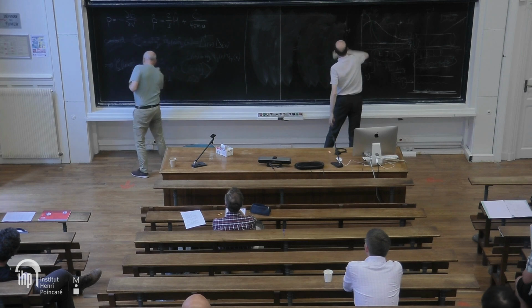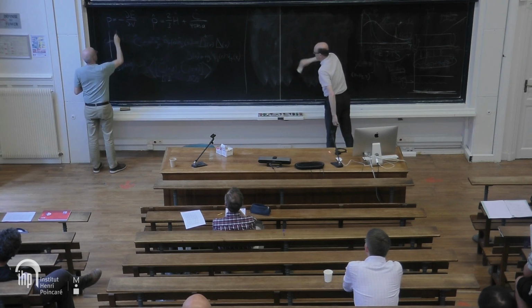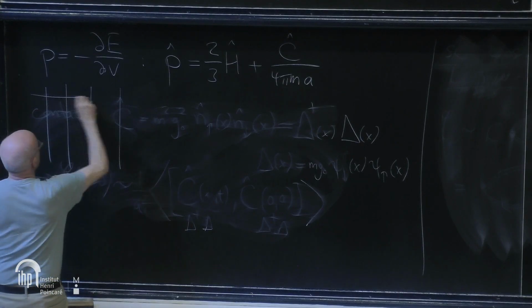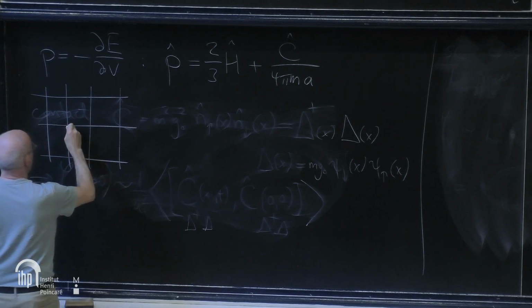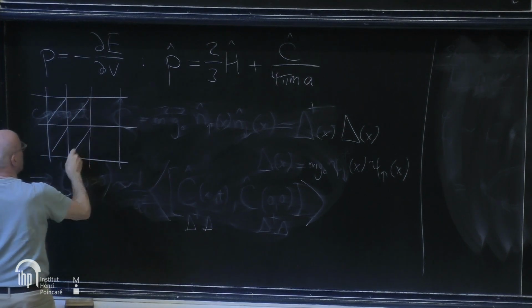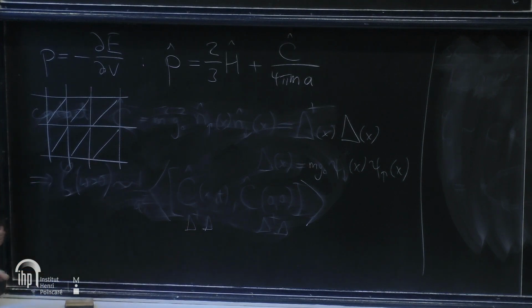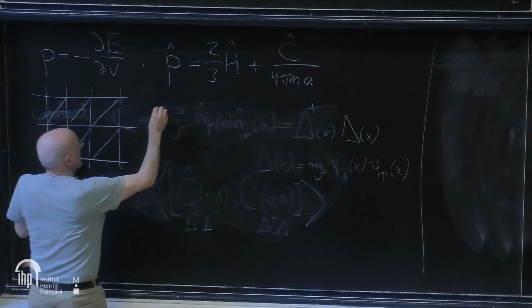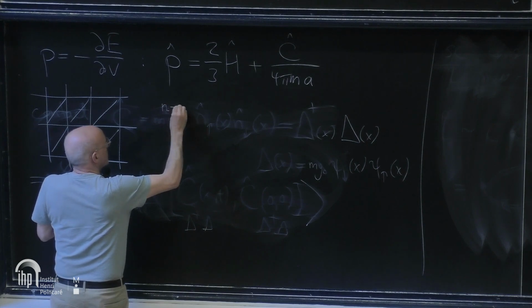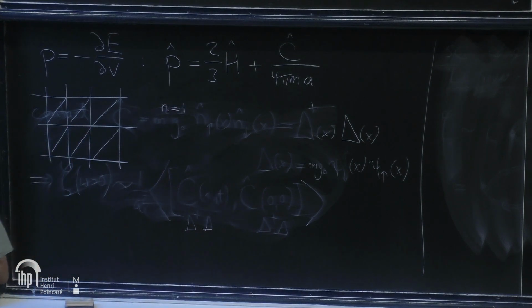So A, it's not the same lattice. The lattice of the organic superconductors is some anisotropic triangular lattice with t' only. You can think of it as a square lattice, but with t' only in one direction, so it's much more frustrated. And secondly, this is not doped. This is one particle per site, right? Studied as a function of pressure. So it's really not the same animal, right?